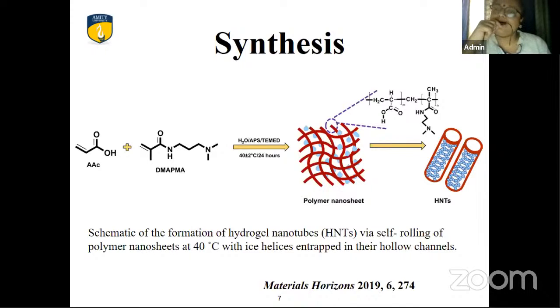So when I looked into the system at the nanoscale, I went on doing the reaction till 24 hours, took an aliquot of the mixture and went for TEM and AFM analysis. I saw that it is a tube-like structure, and this tube-like structure has a helix inside. That inspired me. It might be some new molecule, some new exotic nanostructure, because it is very unnatural. They have already said that it is a pH-sensitive polymer. It imbibes at an alkaline pH, and it can deliver the payloads, the drugs, and it can help for colon cancer or other treatments, as has been reported.